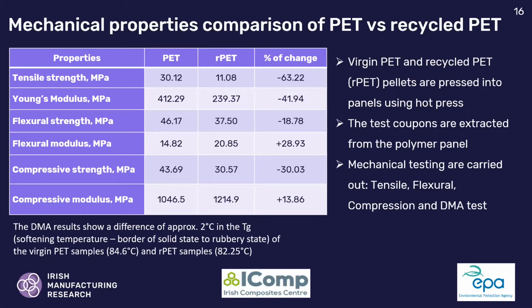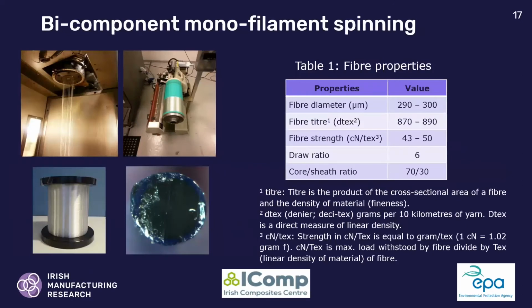So both PET and rPET are very close, with around 2 degrees Celsius difference. The Tg is like a softening temperature. It's a border temperature where the solid state becomes a rubbery state. And the next stage is to develop a bicomponent monofilament, which is carried out at Centexbel VKC, Belgium.